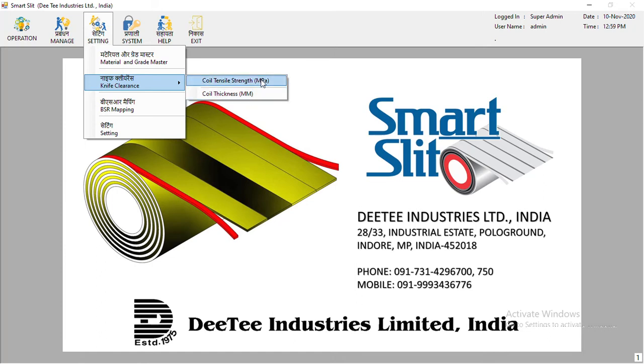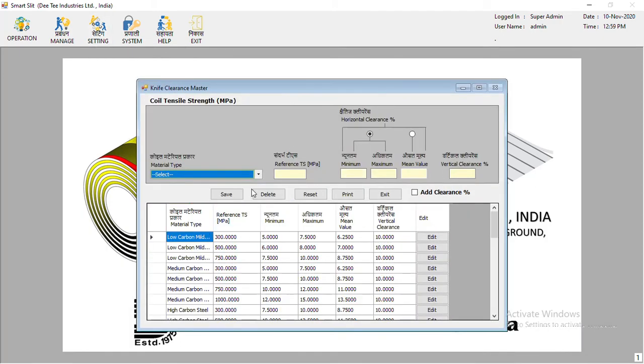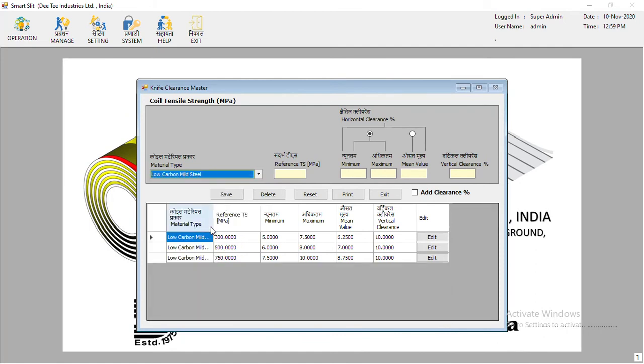Again, it is based on customer requirement only. Some customers want to have that type of table. Just for example, I select low carbon steel. For low carbon steel, my user was telling me, this is my practice: up to 300 tensile strength, I use 5 to 7.5% clearance. For the range 300 to 500, I am using 6 to 8%, and for 500 and above, I am using 7.5 to 10%. Like that, the customer was demanding.